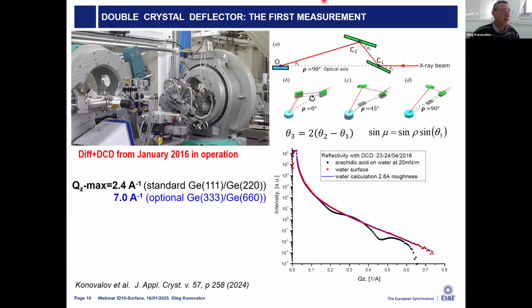So this is a bit of a flavor of how the deflector works. What you see here, the turntable, holds 2 crystals. This is, let's say, a side view or top view. So there is a beam. Then there is one crystal which deflects the beam by back reflection. Usually what works is germanium 111. Then the second crystal deflects the beam back. This is germanium 220, so that the Bragg angle of the second crystal should be bigger than the Bragg angle of the first crystal. And then it goes to the surface of the sample, at the point where this beam intersects with the initial beam. If we rotate this part as a whole, solidly, we can change the grazing angle on the surface without changing the Bragg angle on the crystals.